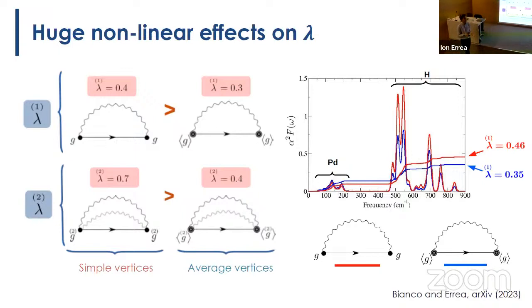Because as we are calculating the free energy, the electronic susceptibility enters in this free energy. So it's there, and we have all the effects, all nesting effects. If nesting is the source of the electron-phonon instability, it appears in the calculations as well. Then later you need to search for the origin in other signatures somehow. But it's not something that I am assuming. If it's a different scenario, it will come out as well. The instability will come out.